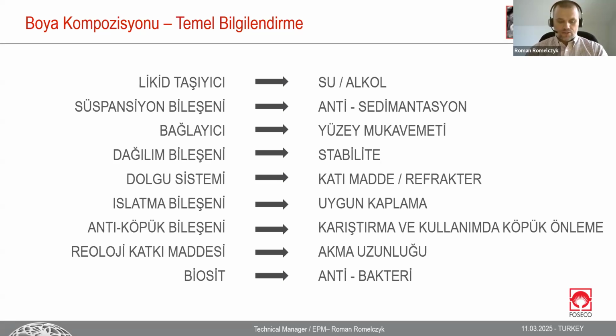So this suspension agent takes care of keeping the solids suspended in the whole volume so they do not sediment. Another one is the binder. The binder is the part of the coating which takes care of the coating in the dry phase. After application, we dry the coating and we expect some mechanical strength from it. That means adhesion, but also mechanical strength itself, to prevent, for example, powdering or peeling off. So the binder is also responsible for that.